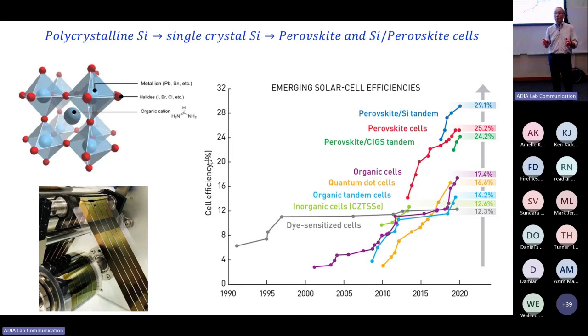And so you ask them why, and they say, well, look at the physics of what was going on. These grain boundaries were moving around. They would be recombination sites. We stabilized the grain boundaries, and it lasted longer. So I'm guessing that once these perovskites get to 25 or 30 years, 25 is good enough, they may take over because you need a micron or less of the material to make it. It's low temperature materials, so there's no big energy investment.